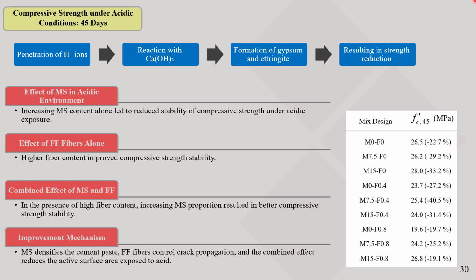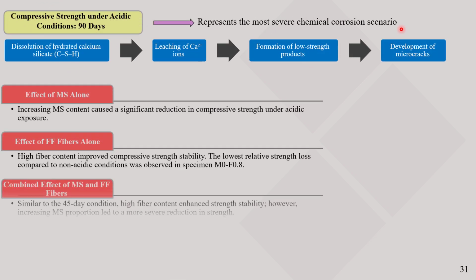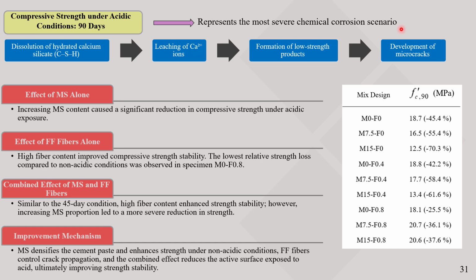Therefore, using both microsilica and fibers simultaneously, high fiber content with a moderate amount of microsilica can create a relative synergistic effect. Microsilica increases cement paste density, while Forta-Ferro fibers control cracks and prevent acid penetration. For the 90-day acidic condition, the same mechanism occurred, but the chemical attack was more severe. The results were almost similar to the 45-day case.